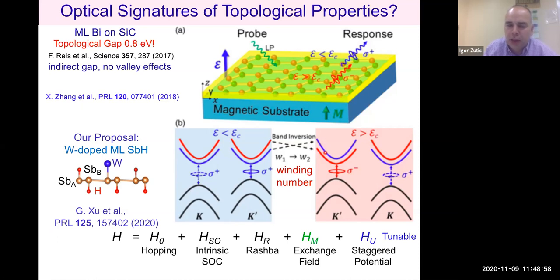And the staggered potential is possible because we have inequivalent atoms. So these two antimony atoms are in a different environment depending on the hydrogen or tungsten atom. They are not equivalent, and this can then give rise to these valley selective effects.